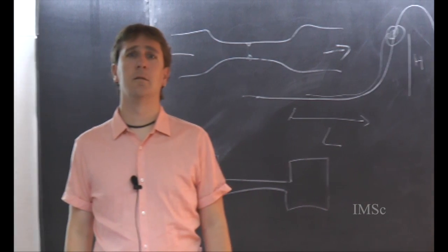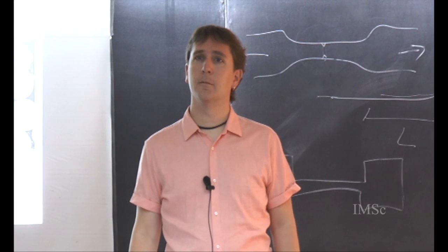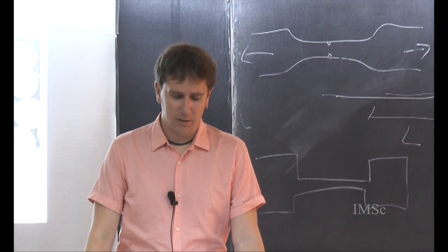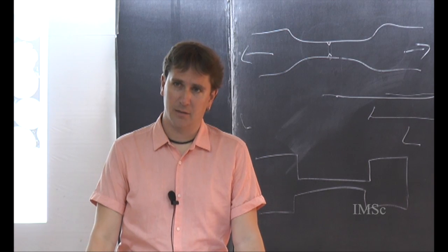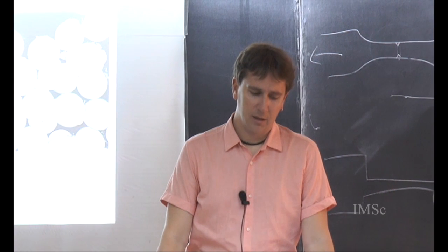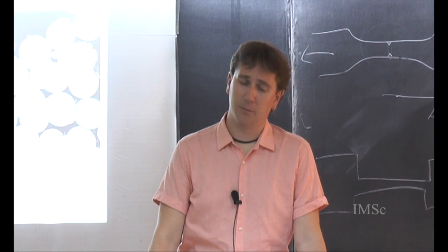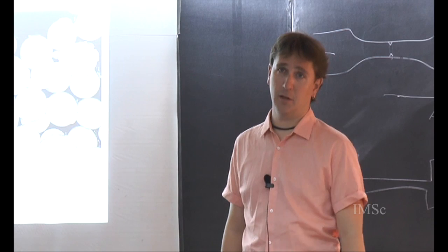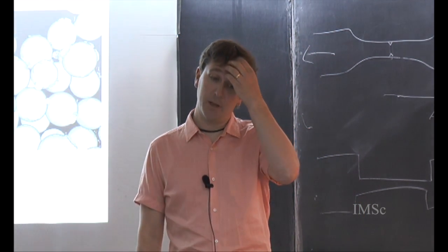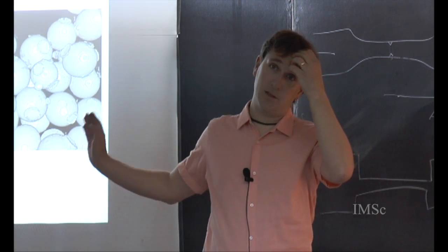Can you tune the failure point by the choice of polymer or the kind of polymer? You mean so we can tune the fracture toughness. The fracture energy we've only changed by changing the contact area. We've not explored other polymers. There will be a different surface interfacial energy associated with different polymers, different surfaces. One thing that probably would affect this is surface roughness.